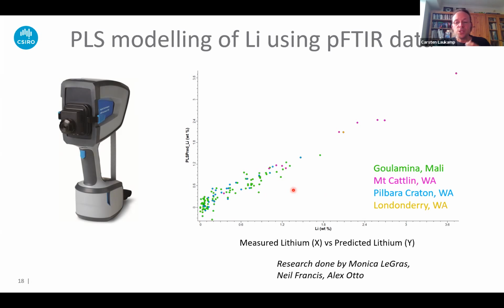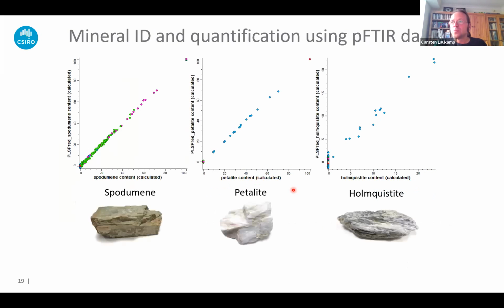With the handheld FTIR, which is really good because lithium is such a light element that we can't detect it with handheld XRF. That's not possible. You can use LIBS, but there might be issues with the volume that we're measuring. The handheld FTIR provides another way of measuring the lithium content if you have calibrated it before. But apart from the geochemistry, you get as a bonus also the lithium-bearing mineral. So you can quantify the spodumene, for example, or petalite or holmquistite, or whatever mineral contains the lithium in that respective mineral deposit.